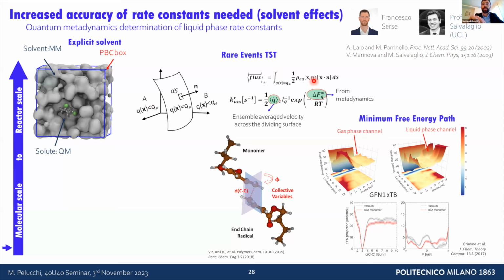One is the free energy change, delta F, and one is the flux along this dividing surface. So we can identify the potential energy surface as a function of the two collective variables, the C-C bond and the dihedral angle.